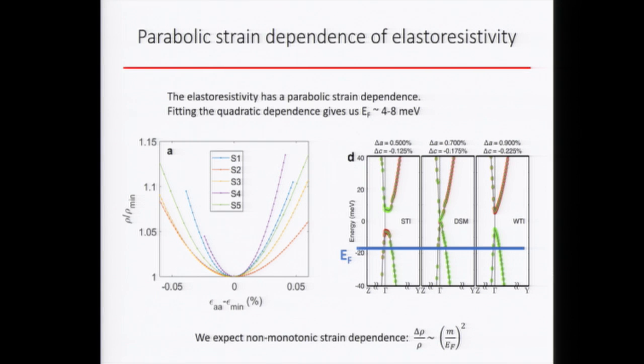The Fermi energy we extract as well for A and B, and then also match with the literature. So it's a very nice way to independently do checks. Another way is that since the Fermi energy is very small, you can increase temperature, and then very quickly you're in a region where the thermal energy is above the Fermi energy, right?